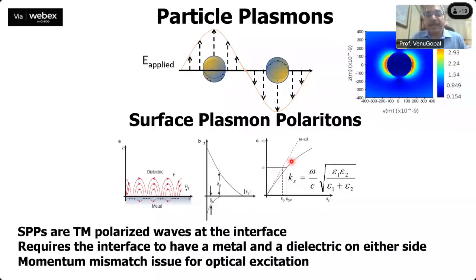Right? And the dispersion relation is given by this: K_spp, the surface plasmon polariton momentum, is given as omega by c times the square root of epsilon 1 epsilon 2 by epsilon 1 plus epsilon 2. Epsilon 1 and epsilon 2 are the dielectric constants of the metal and the dielectric which form the interface. Okay. So when we plot the dispersion, this is the light line, the dispersion for the photon, and this is the dispersion for the plasmons.